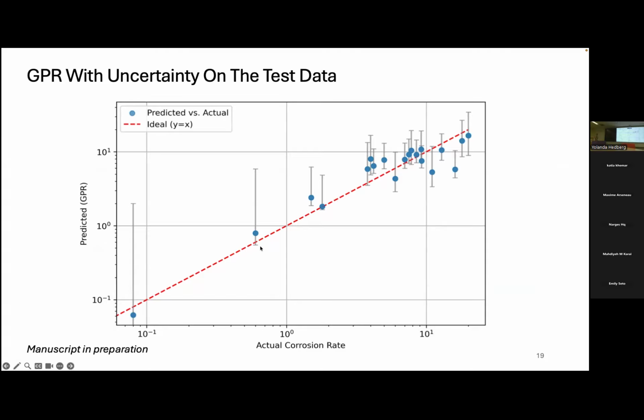And the error bar itself is not coming from some other quantity, but actually this is measuring if the current literature has more data on this input side. So we probably have more samples on the high rate corrosion side because this is aqueous corrosion, and we have less data on the lower rate corrosion side. So this kind of model can actually tell you that if you are having a new system, the error bar in this prediction will work as some estimation for your new experimental setup. And you can use this model as your, say, first-contact model to design the next experiment.